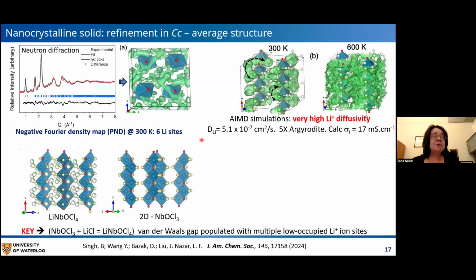So this is an interesting material. It effectively has this chain-like structure, which resembles that of the two-dimensional material niobium oxychloride. And niobium oxychloride is effectively a van der Waals solid because there's very weak bonding between these sheets of niobium oxychloride. So you can think of lithium niobium oxychloride as simply this material plus lithium chloride, where the lithium disperses in between the layers, and the additional chlorine ends up modifying the coordination of the niobium.